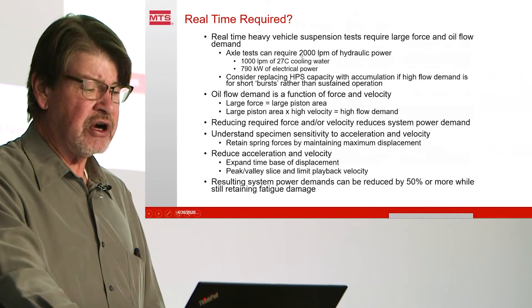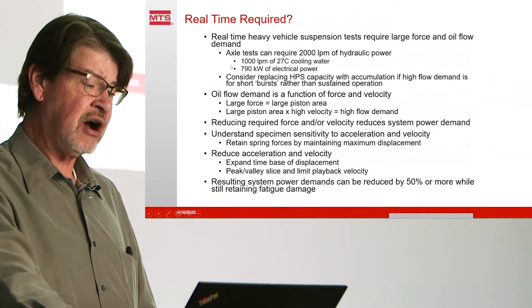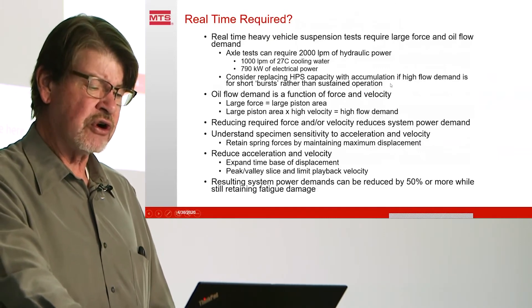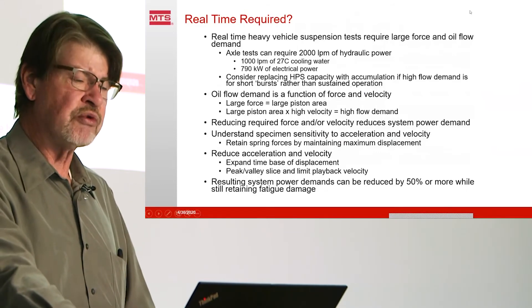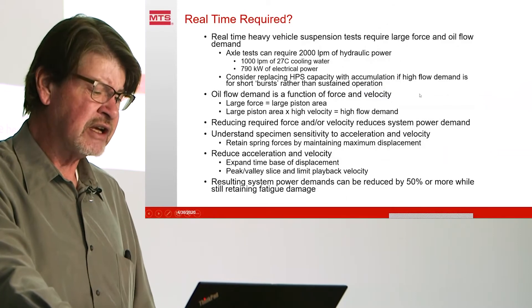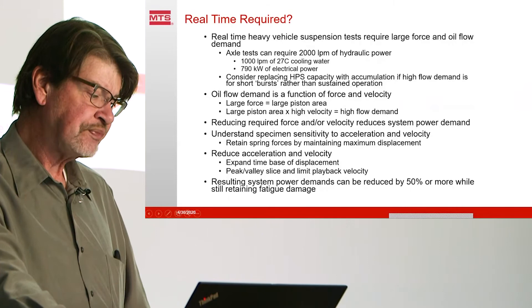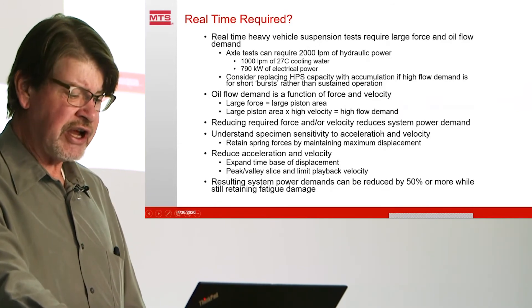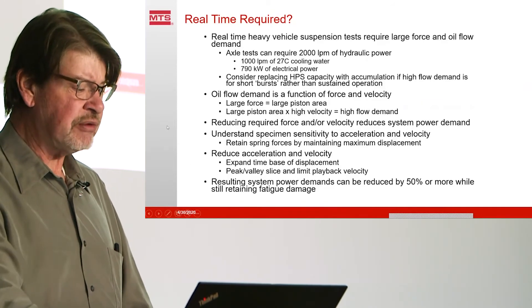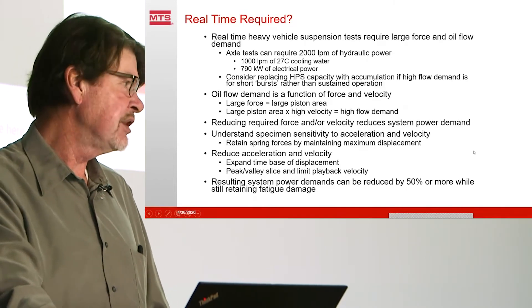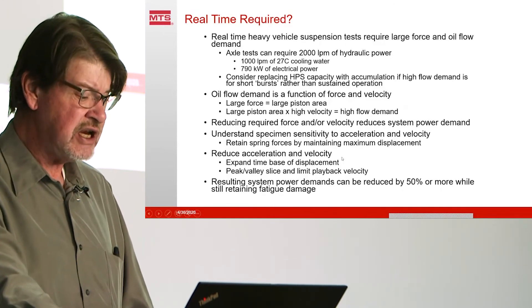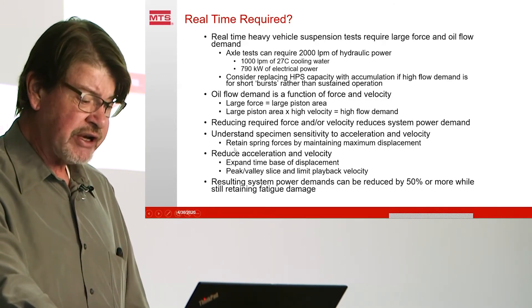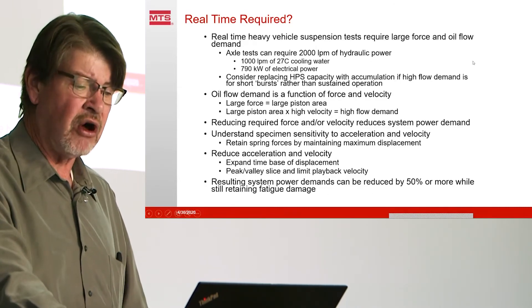Axle tests can require up to 2,000 liters a minute of hydraulic power — that's 790 kilowatts of electric power and 1,000 liters a minute of cooling water in addition to just running the pumps. Consider replacing HPU capacity with accumulation if high flow demand is for short bursts — that might work for hitting a pothole, but not for a washboard road with 20 to 40 seconds of continuous playback. Large force means large piston area; large piston area times high velocity equals high flow. So we must reduce required force and/or velocity to come out ahead. We must understand specimen sensitivity before editing data, and we need to reduce acceleration and velocity by expanding the time base. We can reduce power demand by 50% or more and still retain basically all of the fatigue damage from the field.